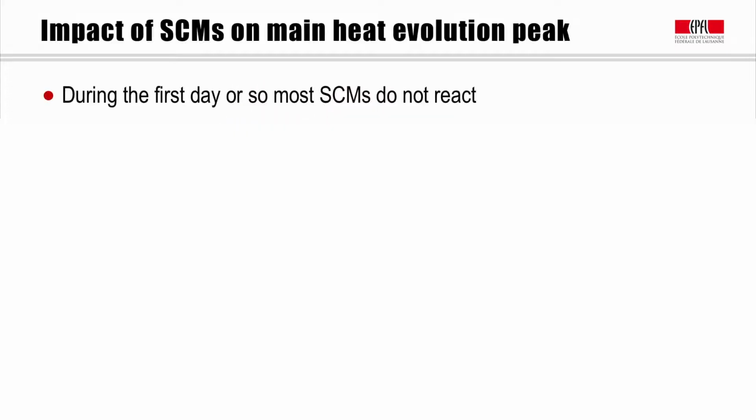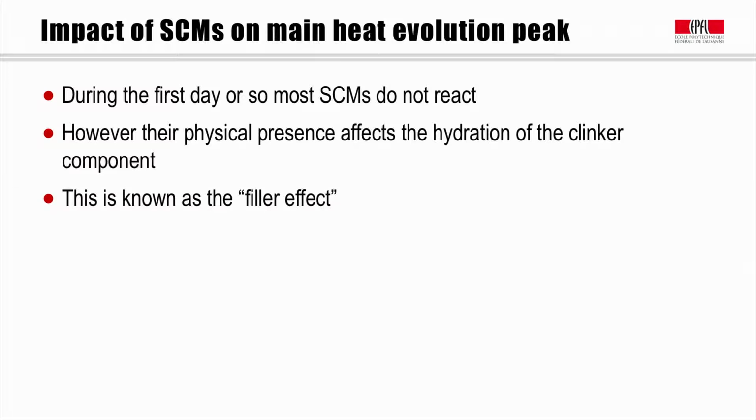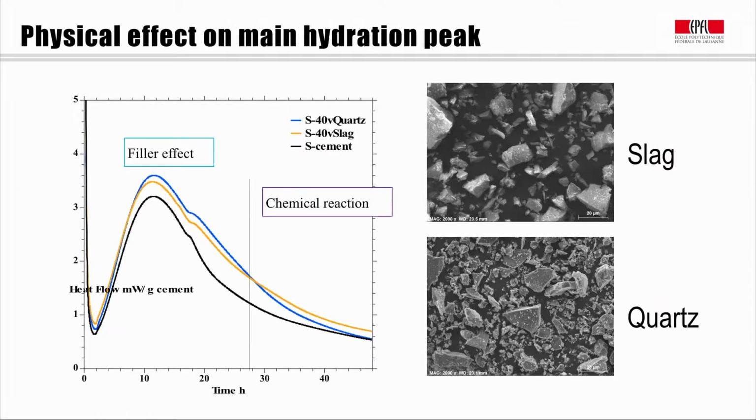This is the impact that supplementary cementitious materials have on the hydration, not because they are themselves reacting, but because of their physical presence in the mixture. During the first day or so, most supplementary materials are not reacting. Their physical presence affects the hydration of the clinker, and this is what we mean by the filler effect. We can see that by looking at this data coming from different mixtures.